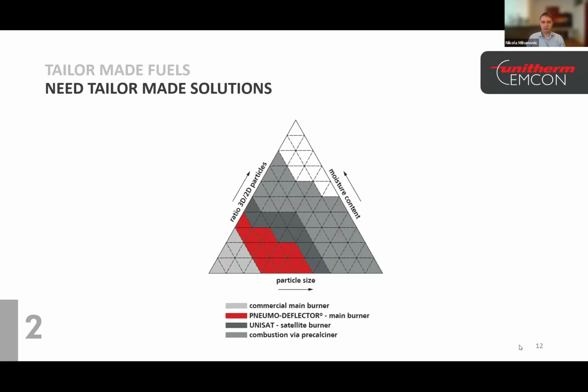However, there are several considerations to keep in mind when starting to fire secondary fuels. Firstly, compared to primary fuels, we need a higher oxygen content at the kiln inlet, typically around 3 to 5%, to ensure complete combustion and to avoid presence of CO at kiln inlet. Additionally, depending on secondary fuel type, we may need to adjust our raw mix to achieve desired clinker quality. For instance, using RDF for plastics often introduce additional sulfur and chlorine into the system.